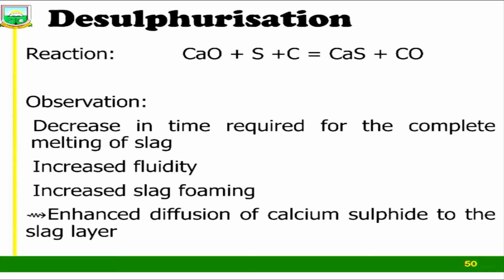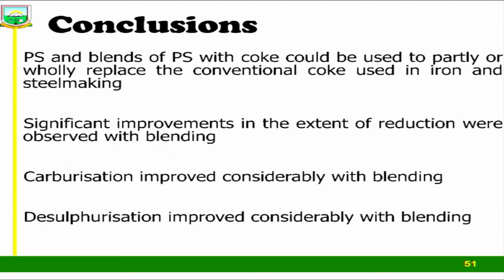We move on to desulfurization. One element that is not a good candidate in iron and steelmaking technology is sulfur. Another one is phosphorus. Accordingly, anytime you want to produce your metal, you check for your sulfur and then your phosphorus content. We wanted to be sure that when we use our polymer, desulfurization will be better, and truly, when we measured the content of sulfur, the metal that was produced using the polymer was far superior to the conventional way of producing your metal. These are some of the conclusions that we drew.